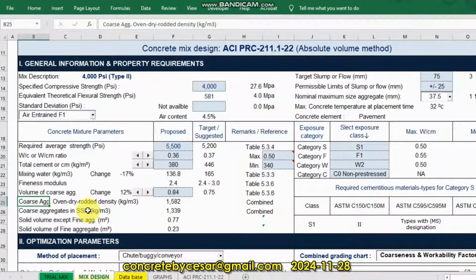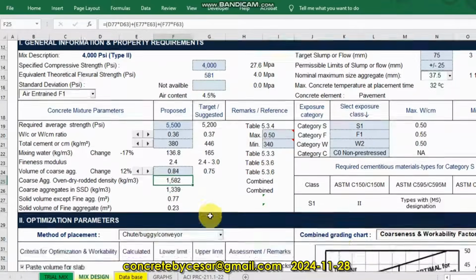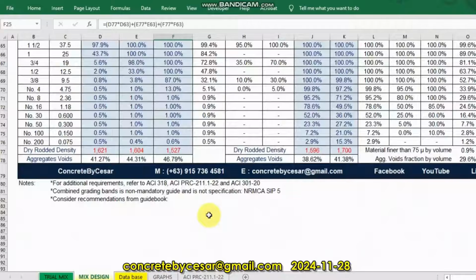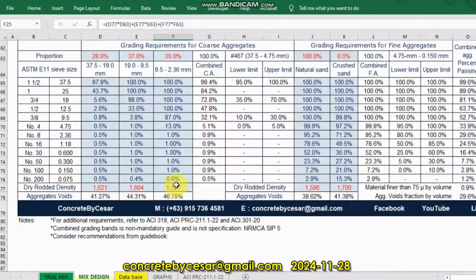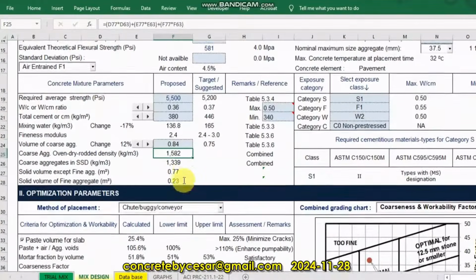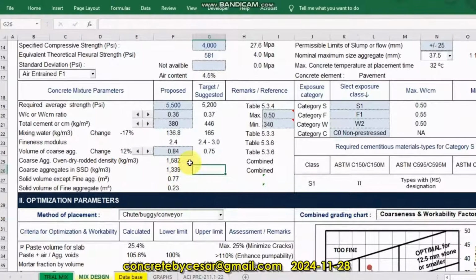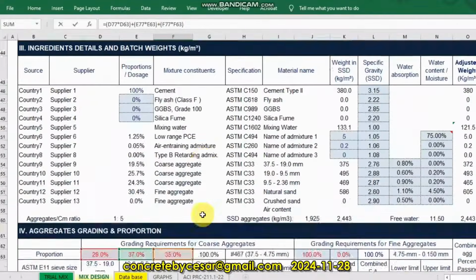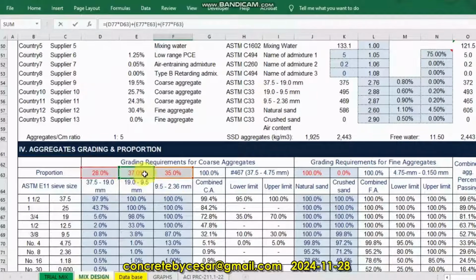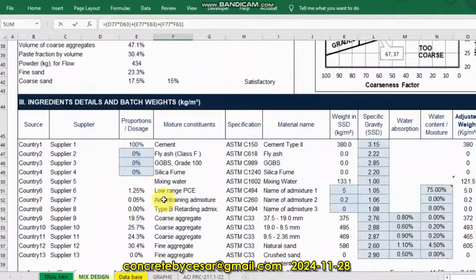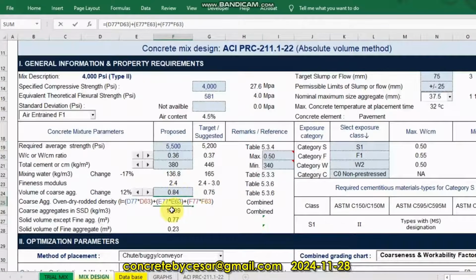For the coarse aggregate oven dry rodded density, from the beginning, as I have mentioned, once you update the dry rodded density, then automatically it will be combined here. That will be the result of combining these three aggregate sizes. Our oven dry rodded density will be 1582 kg per cubic meter.